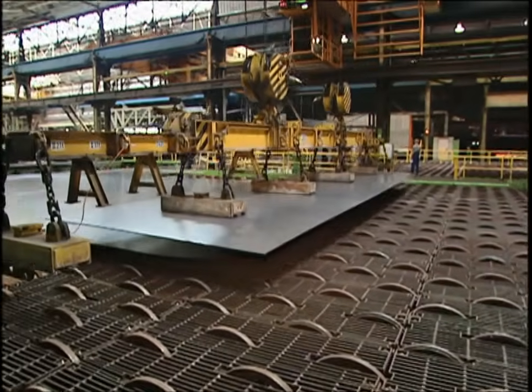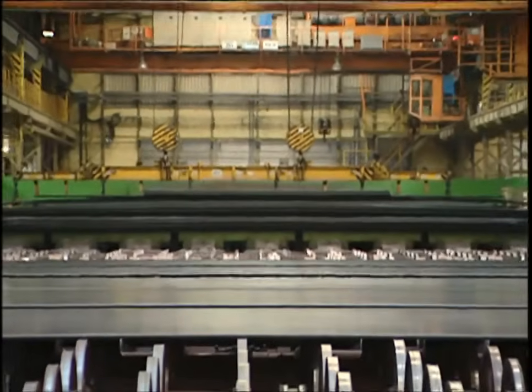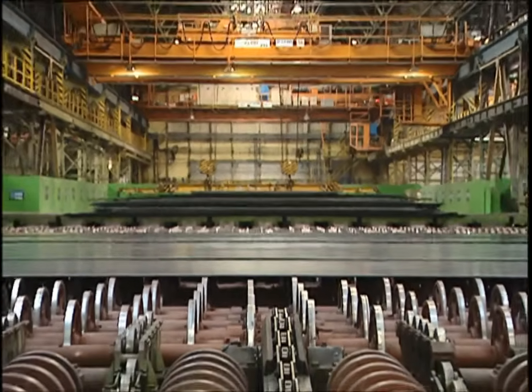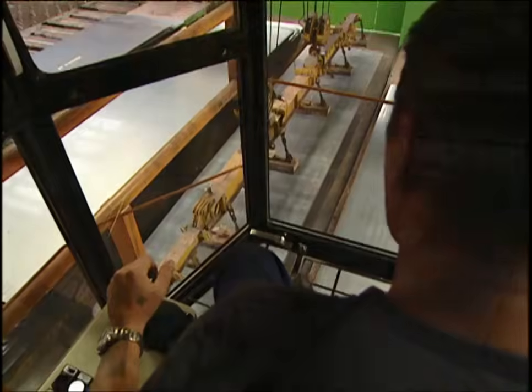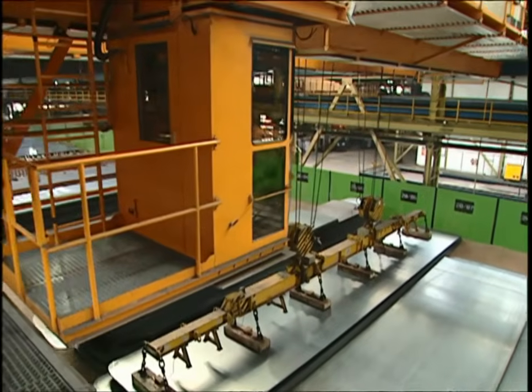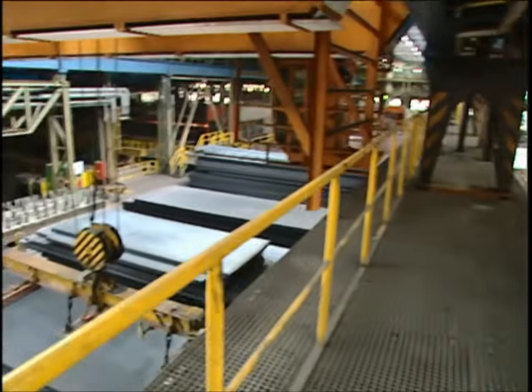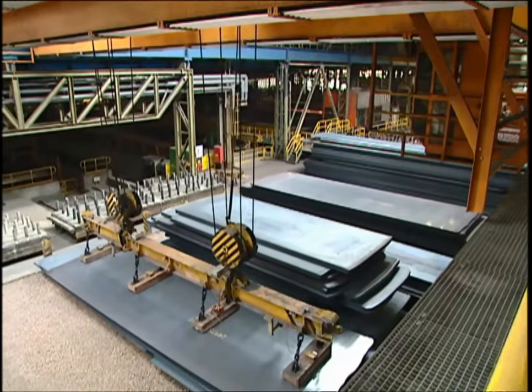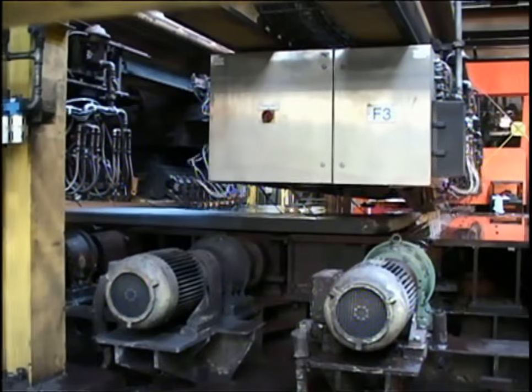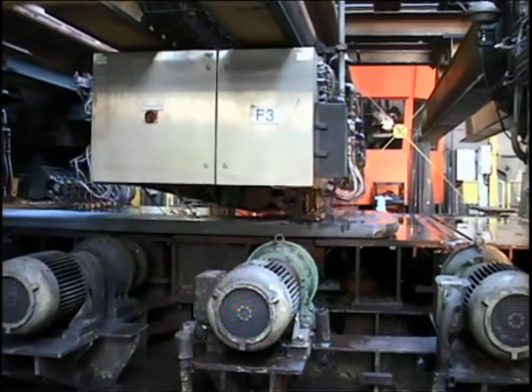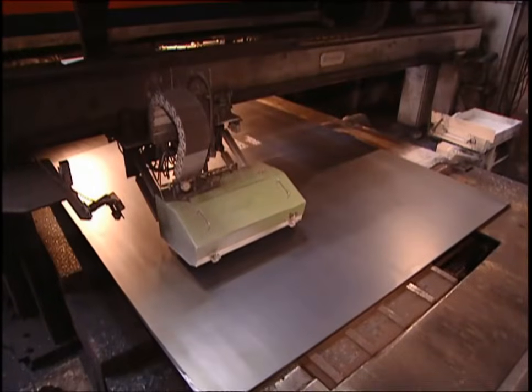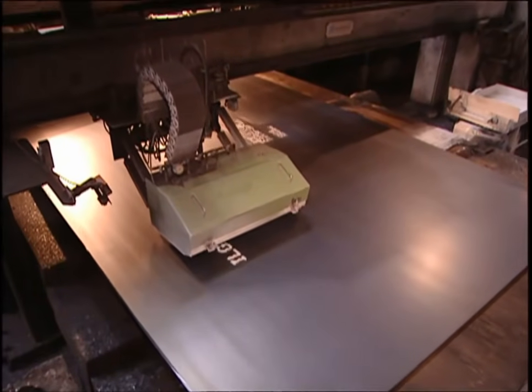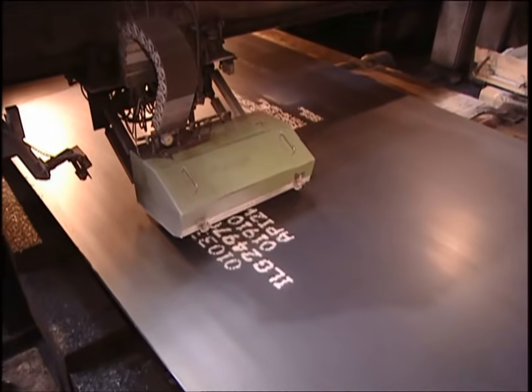Depending on the thickness, the plates are cooled in stacks before undergoing surface inspection. During cooling, the effusion of hydrogen from the plate takes place in order to prevent hydrogen-induced cracks. Ultrasonic testing is used to ensure the steel plate does not contain any internal defects. This is followed by customer marking complete with order data to identify the plate.